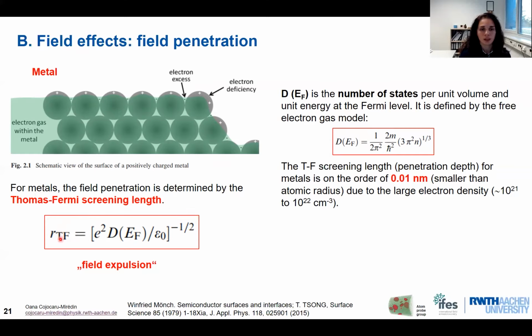So the screening length is inversely proportional to the number of states per unit of volume. But the number of states is defined by the electron gas model, as usually we do, and this is directly proportional to the electron density. Now we know for the metal that the electron density is pretty high, about 10 to the power 21 or 10 to the power 22 per cubic centimeter. So that means for the metal, we have in general a pretty high number of states. Pretty high number of states, if we insert it in this formula, means a pretty low screening length.